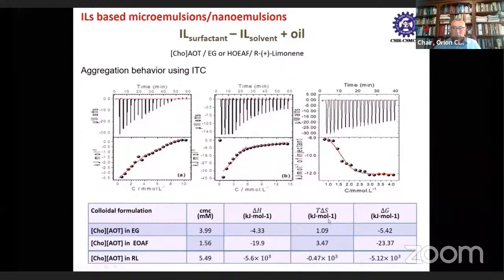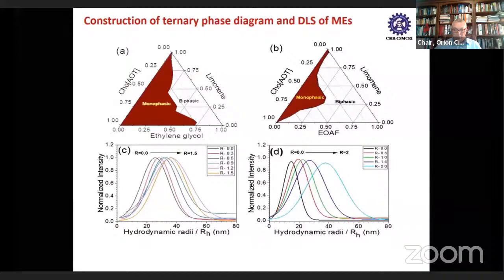And from the thermodynamic properties derived, we can see that delta G of aggregation is negative in all the cases. So there is a very good feasibility of aggregation of choline AOT in ethylene glycol as well as hydroxyethyl ammonium formate and in limonene. So by finding that these can be aggregated in ionic liquid medium or ethylene glycol medium, we constructed the microemulsions of these components. Here we can see the ternary phase diagrams of choline AOT in ethylene glycol with limonene as an oil phase. And in the right side ternary phase diagram, we have replaced ethylene glycol with hydroxyethyl ammonium formate as a polar phase. And in both the systems, we found that there is a very large monophasic region which is formed without using a co-surfactant.